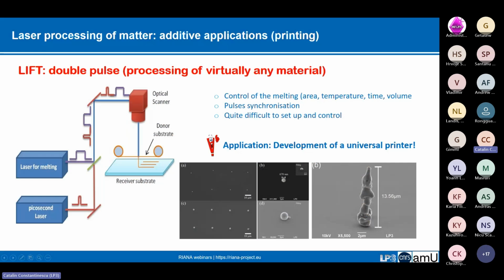So in this case, we used double pulsed lift developed in LP3 by our colleagues Patricia Aloncle and Philippe Delaporte. This was a thesis a few years back, and the whole process is really simple. Instead of using one pulse to print, we use two. So we start from a solid thin film donor, and we use a first pulse of a laser, microsecond for example, that will interact with the donor. It will melt locally the donor. It will create a pool of molten material, and then a second pulse will just eject this melted material and create a droplet.